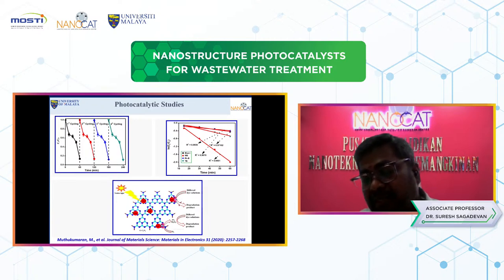And then there's a mechanism. You can see that during the degradation process, following the light irradiation, the surface absorbs oxygen atoms and makes use of the separated electrons in the conduction band of cuprous oxide from this composite to generate the superoxide radicals, O2 minus. In a similar way, the holes in the valence band of the composite participate in reactions with the surface-absorbed water or OH minus to produce highly reactive radicals in this aqueous medium. So this is a potential material for wastewater treatment applications.